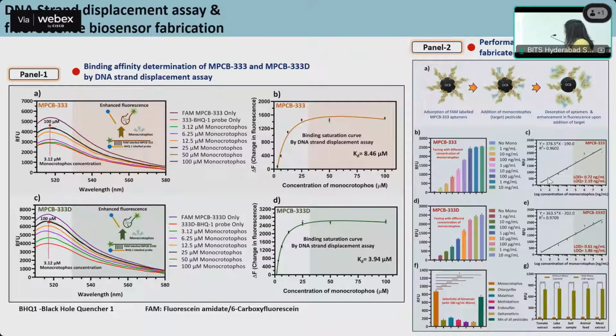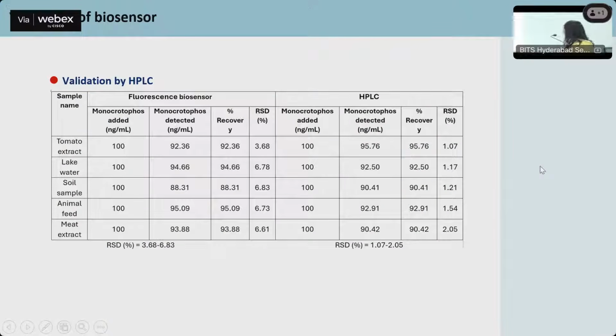Yeah, so you can see this is the mixture of all the pesticides. So this aptamer was very good. And other real samples were also tested. So here you can see there is a huge difference in the RFU value as compared to the control. So we were quite sure that this aptamer which we have selected for the studies is good enough. Yeah, so the validation again was done by the HPLC for this fluorescence biosensor, which is in correlation with the